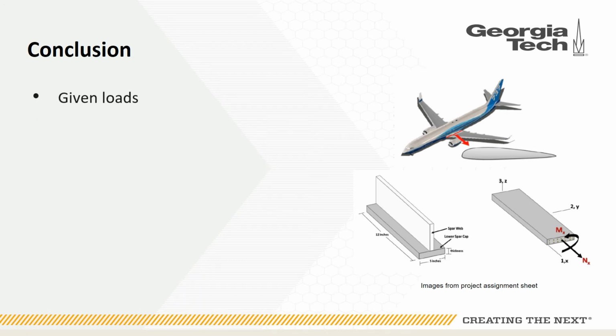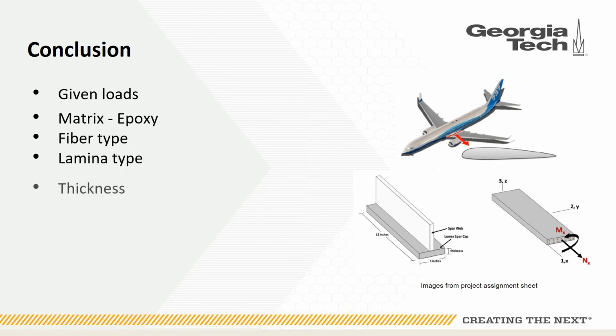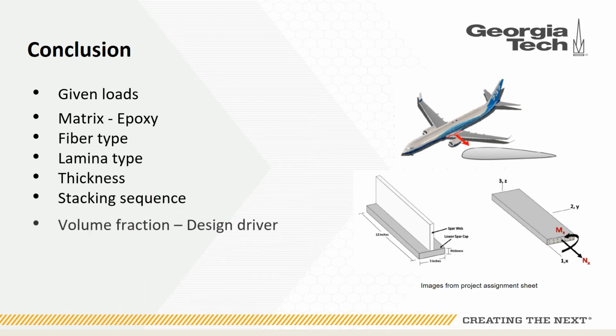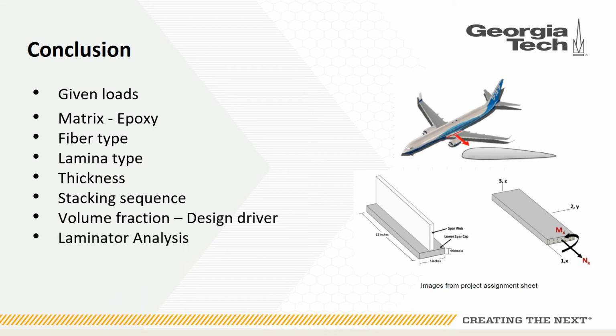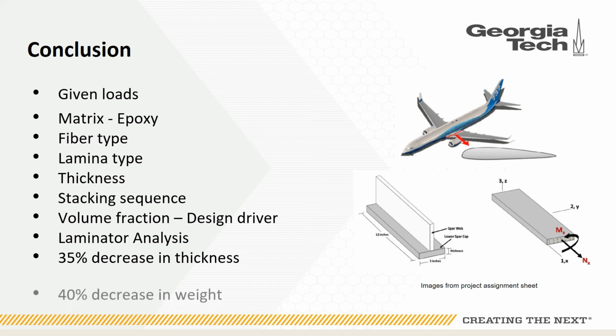In conclusion, given the loads for our composite spar cap, we discussed the epoxy used, the fiber type, the lamina type, the thickness, and the stacking sequence, and we discovered that the volume fraction was the overall design driver. We used the Laminator for all of our analysis and given outputs, and we were able to come up with a 35% decrease in thickness, a 40% decrease in weight, which led to an overall 60% decrease in cost.